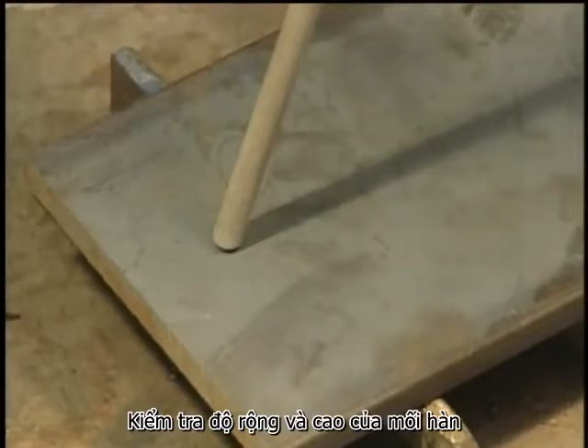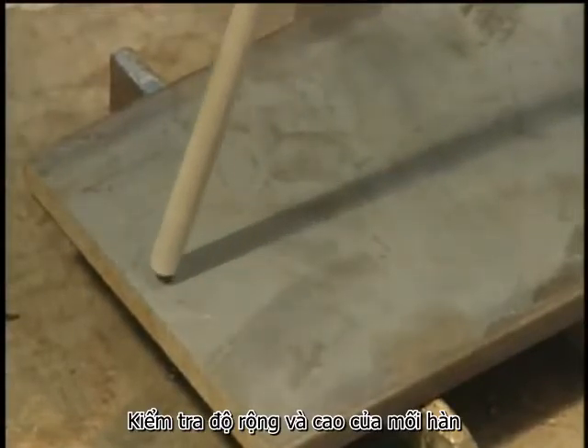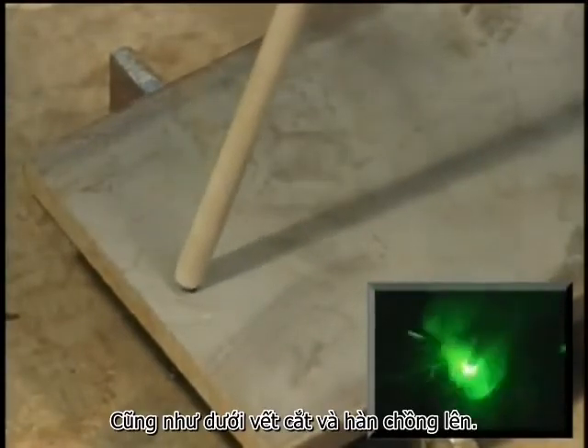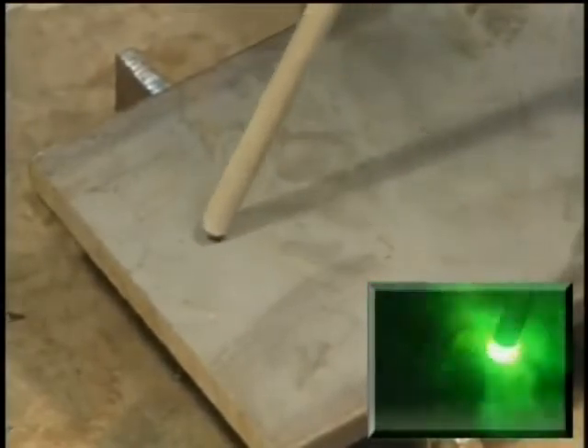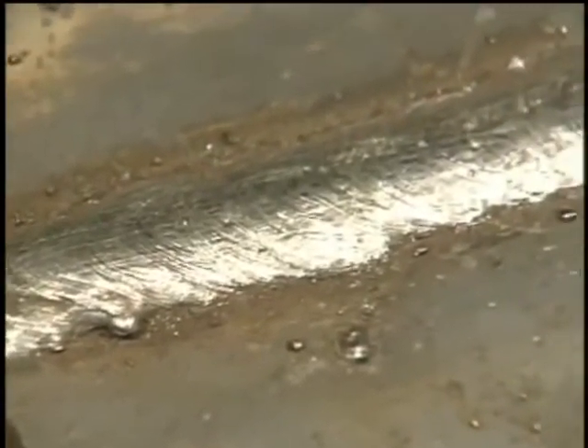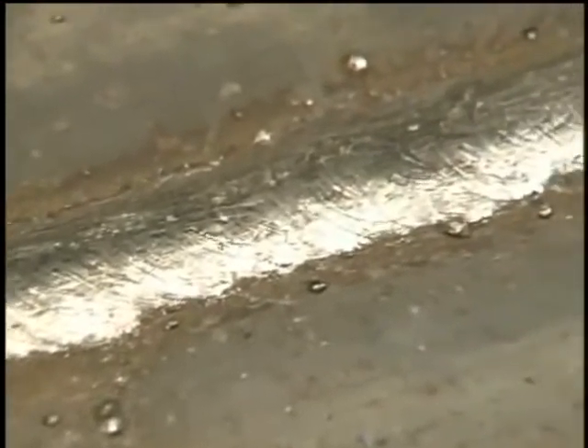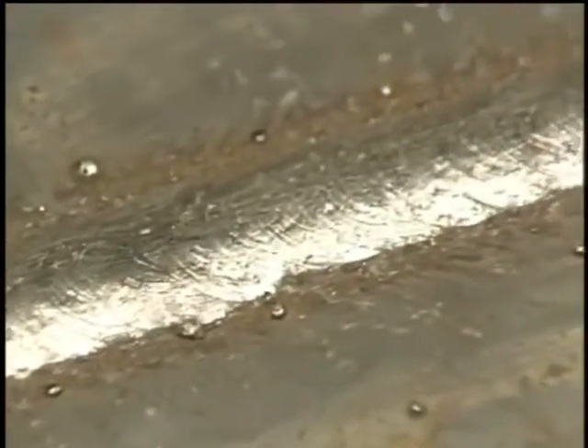Weaving beads are also formed with the welding rod at a 10 to 15 degree angle to the direction of the weld. The width of the weaving action should be 3 times the diameter of the welding rod, and it should temporarily hold the weaving at both ends. Check the bead width and height, as well as the undercut and overlap.